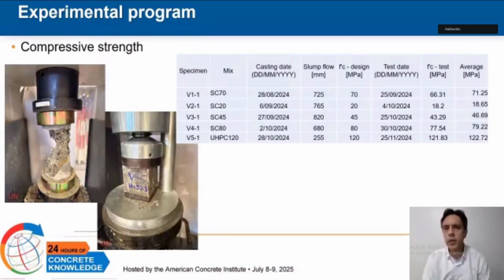In general, all mixtures met or exceeded their design strength targets. For instance, SC20 achieved an average strength of 18.65 megapascals, which is within acceptable variation for low-strength self-consolidating concretes. The SC45 and SC80 mixes achieved average strengths of 46.69 megapascals and 79.22 megapascals respectively, indicating good consistency and alignment with mix design expectations. The UHPC mix reached an average strength of 122.72 megapascals with minimal dispersion across specimens, highlighting the effectiveness of matrix densification and fiber reinforcement.